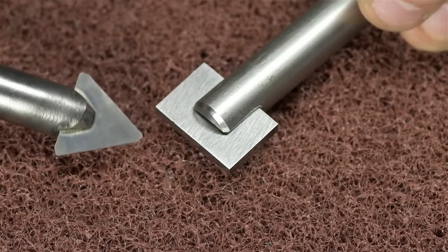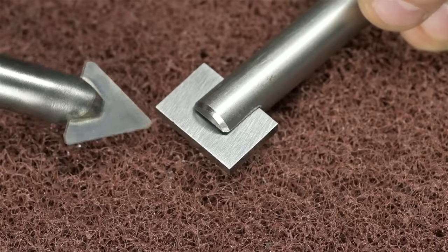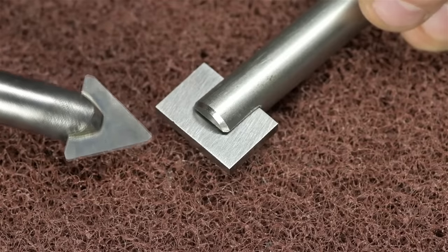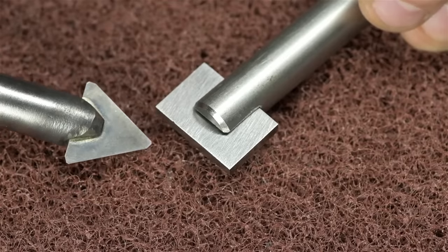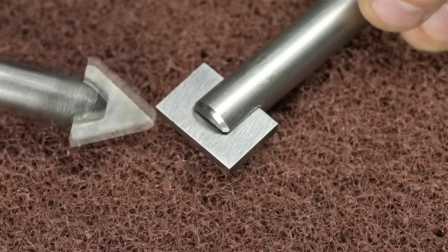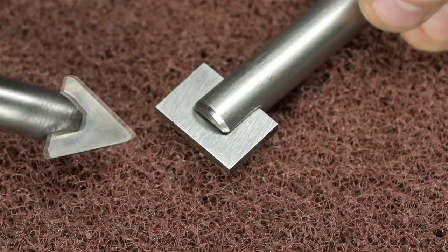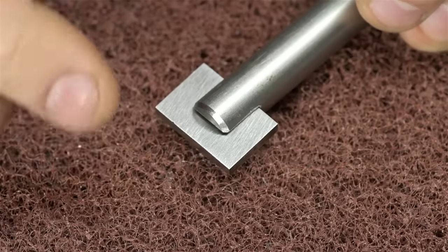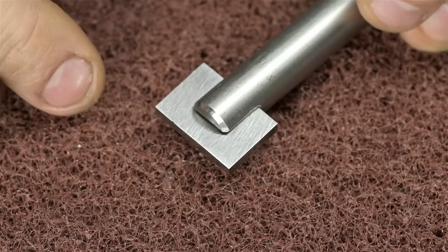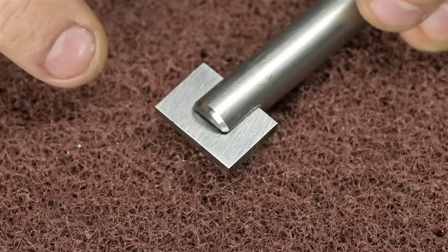Now, you can buy the good stuff, the higher quality high-speed steel that has a higher, like I guess, annealing temperature. Gives you a little bit more breathing room, but you still need to be careful. If you're doing this in an automated setup, like an induction heater you can program for power and time, it's not a problem at all to braze high-speed steel. But with a torch, I don't know, you're really pushing your luck. Now, fortunately, there's another way to attach high-speed steel.